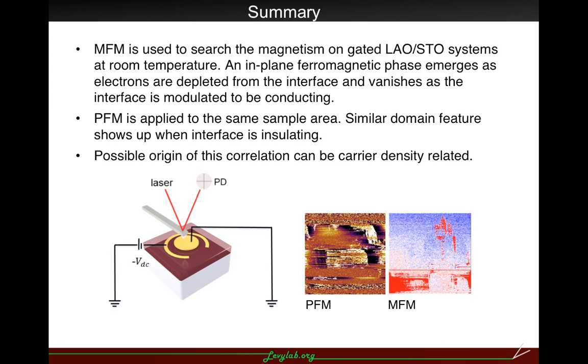For a short summary, MFM is used to search for magnetism in the gated LAO-STO system at room temperature, and the ferromagnetic phase will emerge when the sample is insulating and vanish when the sample is conducting. And PFM is applied to the same sample area, and the similar domain feature shows up when the sample is insulating. The origin of this correlation is carrier density related.